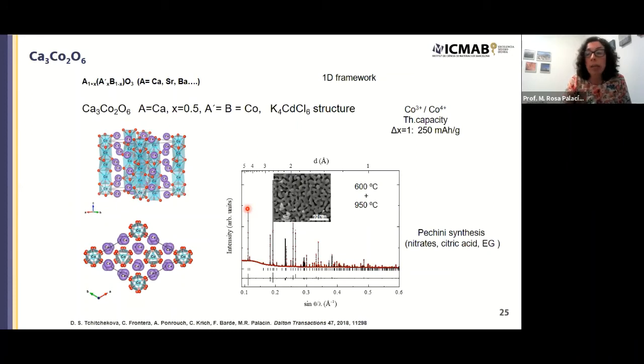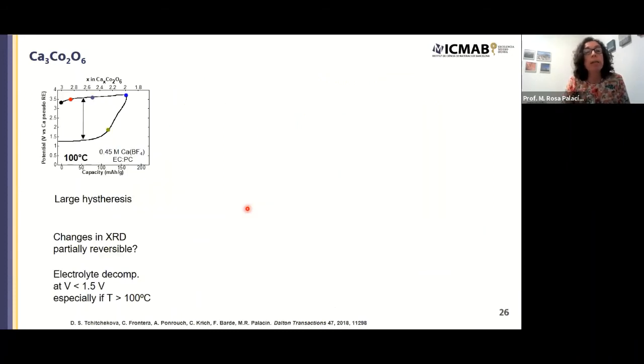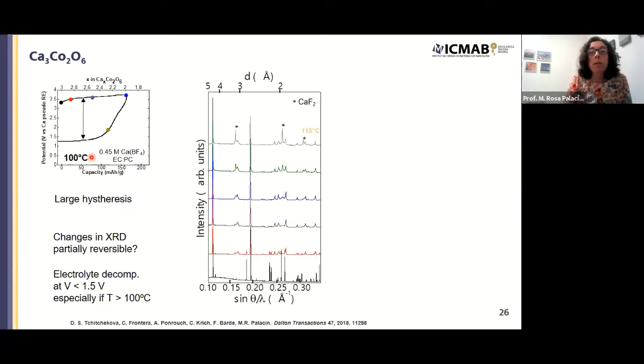So they are really very easy to prepare. And when we try to oxidize and reduce electrochemically, this is what we get. There is a huge polarization between oxidation and reduction, which is indicative of not very good kinetics. But luckily, when we do X-ray diffraction, we see that something is going on here in black.